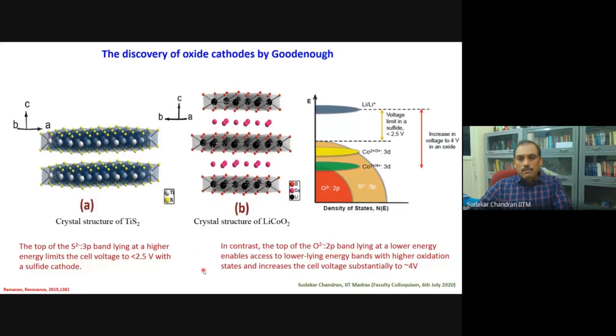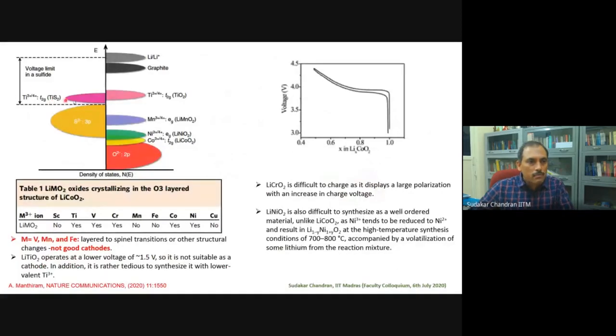Being a solid state physicist, with his basic understanding from 3 decades of working on transition metal oxides, he realized that the maximum voltage you can get from the sulfides is less than 2.5. That is because the sulfur 3p bands lie much higher, just below the lithium redox. So the voltage is only 2.5. In the case of titanium disulfide, the titanium bands, which are just 0.2 eV above this, give about 2.3 volt.